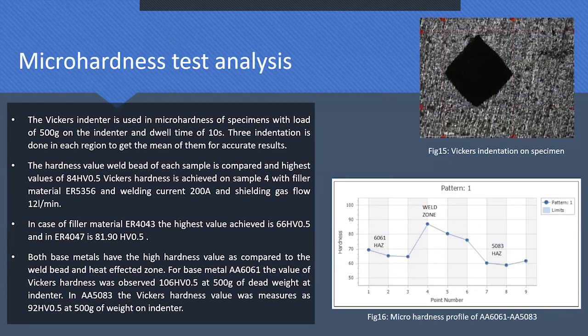Now coming to micro hardness analysis. The Vickers indenter has been used with a dead load of 500 gram and a dwell time of 10 seconds. At right, the indent can be seen in the picture. The highest Vickers hardness value achieved is 84 HV 0.5, where 0.5 represents the dead load of 500 gram, on the sample with filler material 5356. In the case of the two other fillers, 4043 and 4047, in 4043 the highest hardness value is 66, and in 4047 the highest value is 81. At right, we can see the profile of the hardness, which comprises three zones, two heat affected zones and one weld zone. We can depict that high hardness is seen in the weld zone.